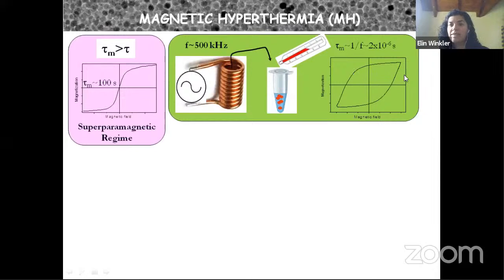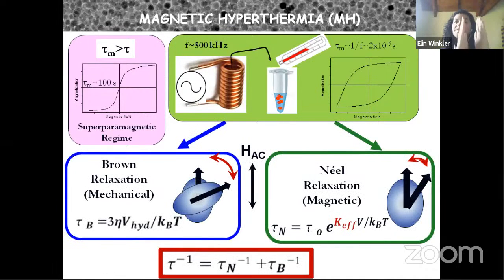In that case, the system presents hysteresis loss. And why is that? Because you have a magnetic moment of the nanoparticle, you apply an AC magnetic field, and there is a phase shift between the magnetic moment of the nanoparticle and the magnetic field. So this hysteresis loss, the area of this hysteresis cycle, is proportional to the energy that is delivered to the medium. So, which is the mechanism by which the magnetic nanoparticle relaxes?